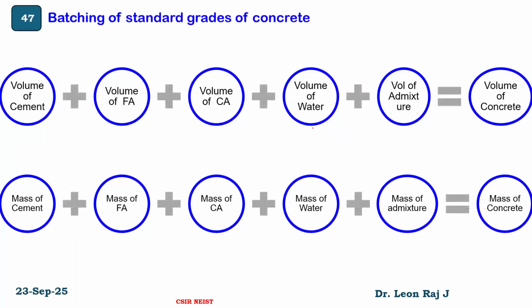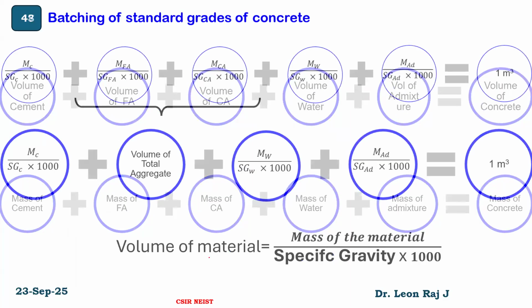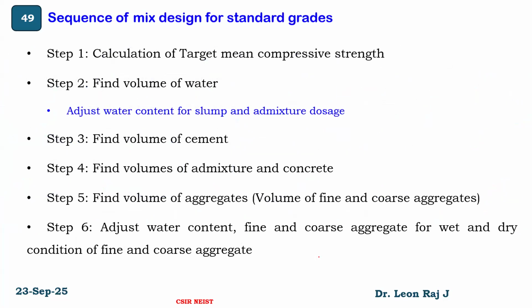Then batching of standard grades of concrete. Volume of concrete is equal to volume of cement plus fine aggregate plus coarse aggregate plus water plus admixture. Mass of concrete is equal to mass of cement plus mass of fine aggregate plus coarse aggregate plus water plus admixture. The volume of the material is equal to mass of the material divided by specific gravity of the material into 1000. Sequence of mix design calculation for standard grades: calculation of target mean strength, find the volume of water, adjust water content for slump and mineral admixture dosage, find the volume of cement, find volumes of admixtures and concrete, find the volume of aggregates, adjust the water content, fine and coarse aggregate for wet and dry conditions.